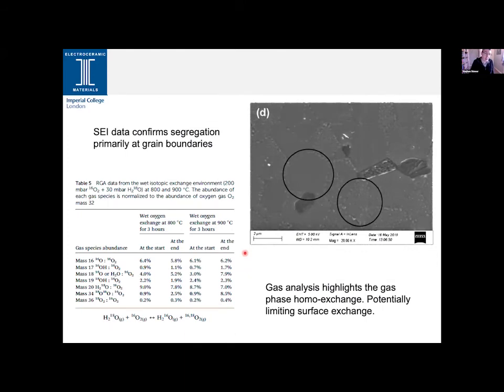So we have our data from the SEI. I seem to have lost my cursor. So the SEI is clearly showing us that we have segregation of species predominantly at the grain boundary. And from further analyses, we can identify that that is indeed those strontium species preferentially segregating to those grain boundaries.